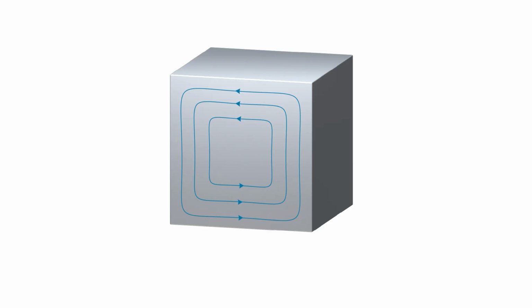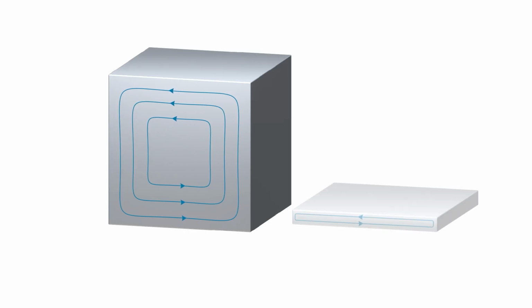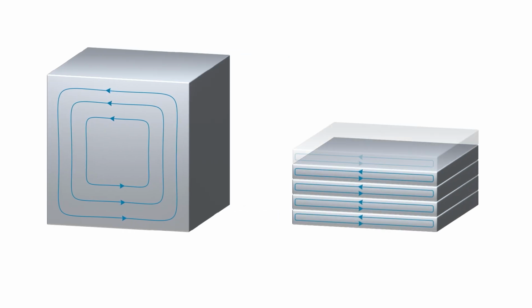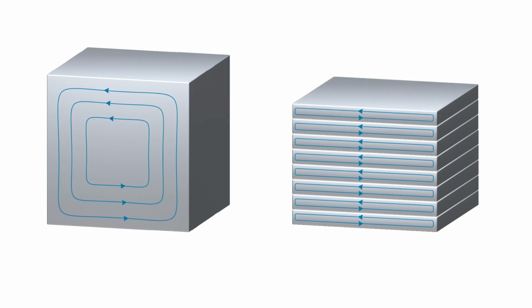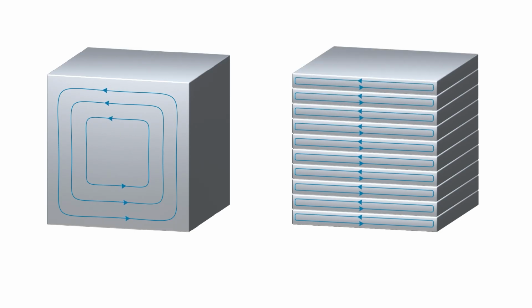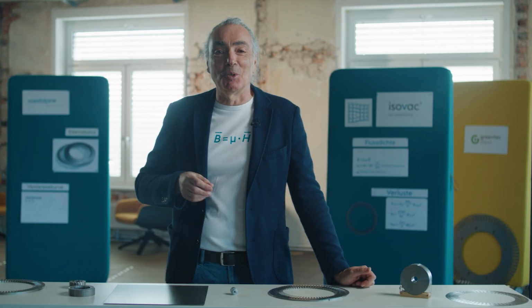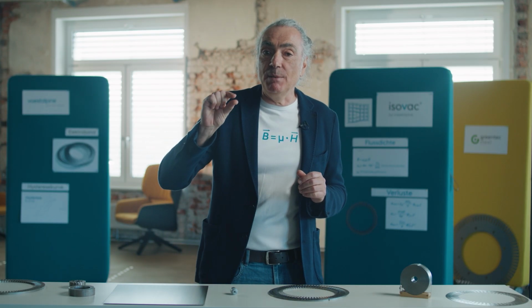Within the material, these currents flow in closed loops. In a solid steel block, these eddy currents can be massive. In thin, electrically insulated lamination stacks, the eddy currents remain small and the loss is low. In the formula for eddy current loss, the frequency term is squared. The eddy current loss is typically proportional to the square of the frequency of the alternating magnetic field. This means that doubling the frequency will result in a four-fold increase in the eddy current loss.